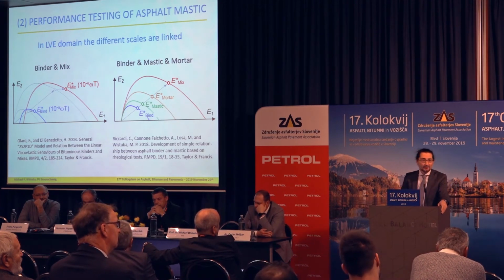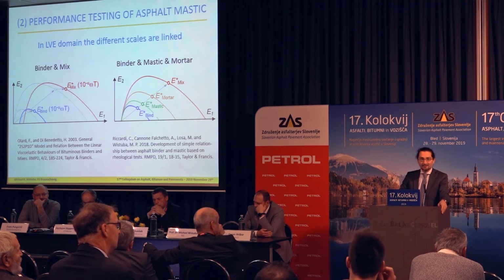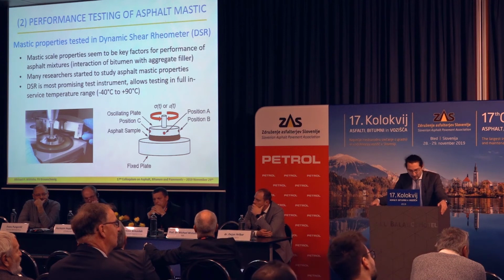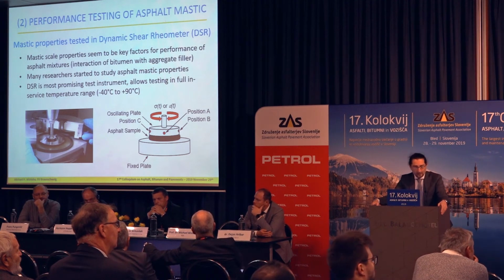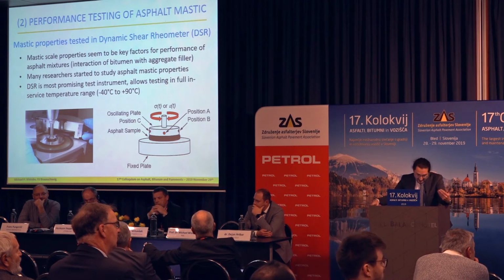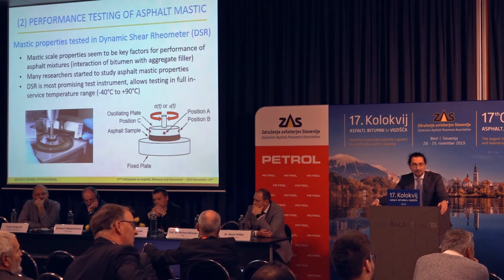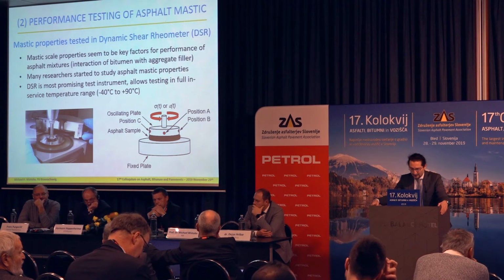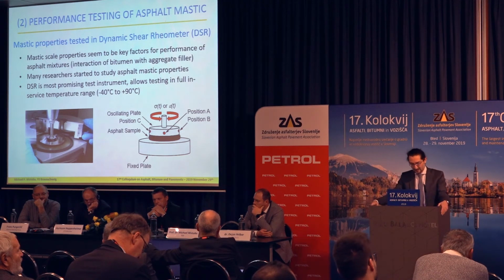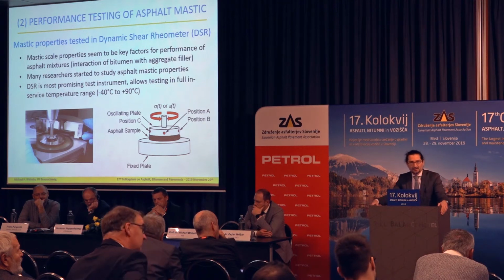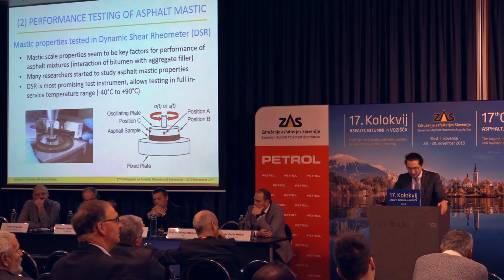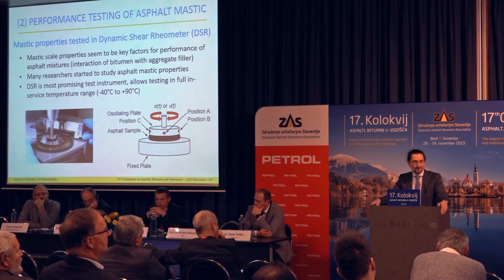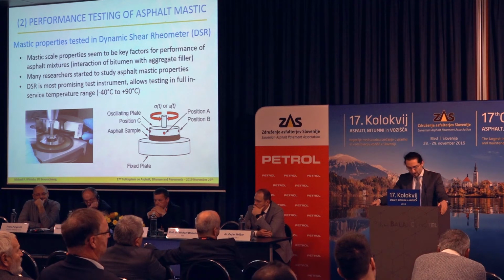So what about when we leave this linear viscoelastic domain? Then we come to all the properties which we are most interested in. So we try to focus on mastic testing also in the domain which is leaving the linear viscoelastic domain. And we do this by mastic testing and not by binder testing, because we learned from previous studies that there could be a big influence of the filler and the filler-bitumen combination on the performance properties of asphalt mixtures. So it is closer to reality if we consider performance of the mastic than performance of the bitumen itself.